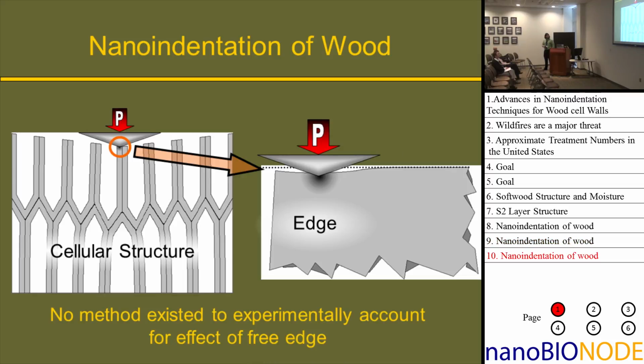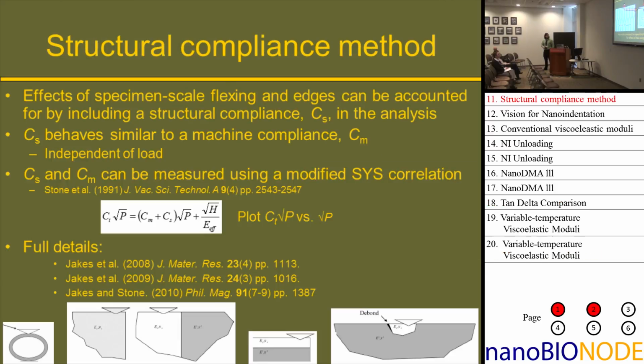And then the other issue is that when you're performing these indents, you're always performing them next to edges, so free edges between the cell wall and the empty lumen, or the edges between the different layers within the cell wall. So back in my PhD at the University of Wisconsin with Professor Stone, we developed what we termed the structural compliance method.